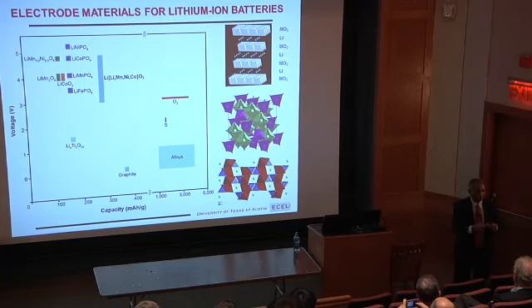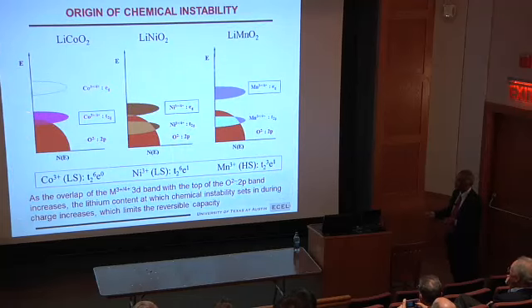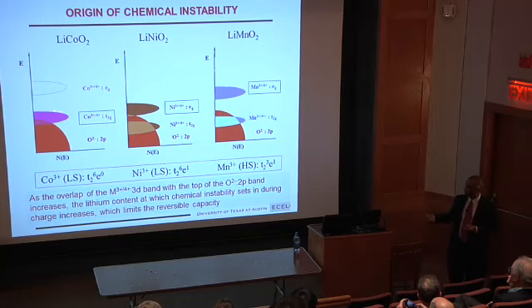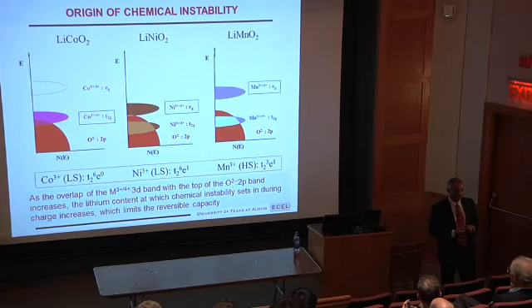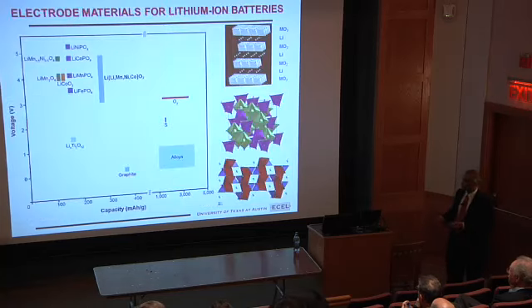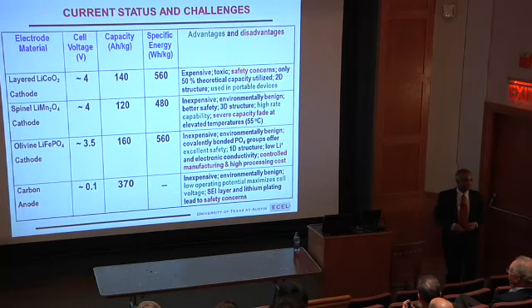And when the current flows internally, the cobalt oxide, because of this problem, will lose oxygen much more easily. So you have shorting, temperature goes up, this guy loses oxygen, lithium cobalt oxide. Then you have all the organic liquid electrolyte present there: big fire, problem. That's how all the safety issues happen. What should we do? Throw this guy out. Find something which will operate at a little bit higher voltage, therefore you will have better